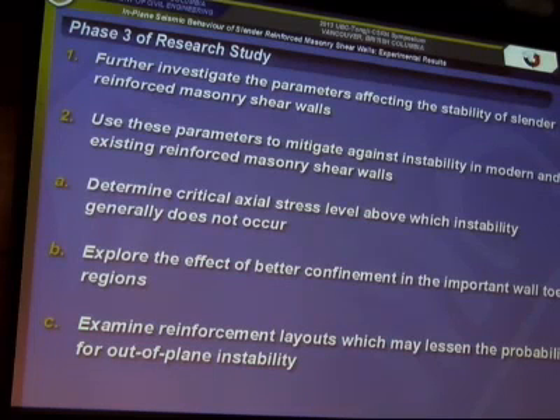So future phases we will possibly be looking at are, again, to further investigate these parameters affecting out-of-plane stability of reinforced masonry shear walls, and also to use these parameters to develop ways to mitigate against this mechanism occurring. Right now, the next set of tests we could possibly be looking at determining critical axial stress, which helps to prevent this mechanism occurring in these walls, and also to explore the use of better confinement in toe regions, which was found to be very important. Another one would be looking at the different types of reinforcement layouts, which we believe will significantly affect this type of mechanism occurring. And that's it for that.